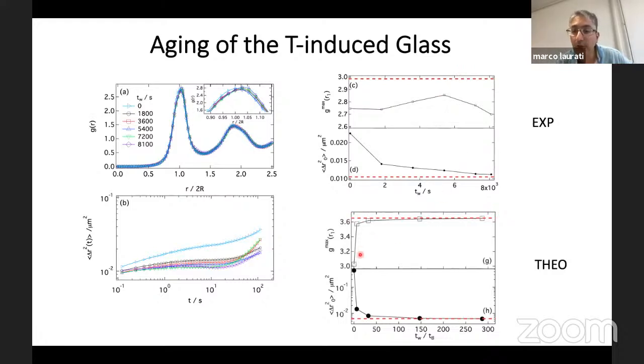Which is actually one difference with the theory. So in the theory, instead, you see that both quantities go at long aging times towards the same values. So this is an indication that this effect on the structure must be an effect of the details, I would say, of the soft particles. Probably it's an effect of what I was mentioning at the beginning, the internal structure of the soft particles, which at the end is a gel network.